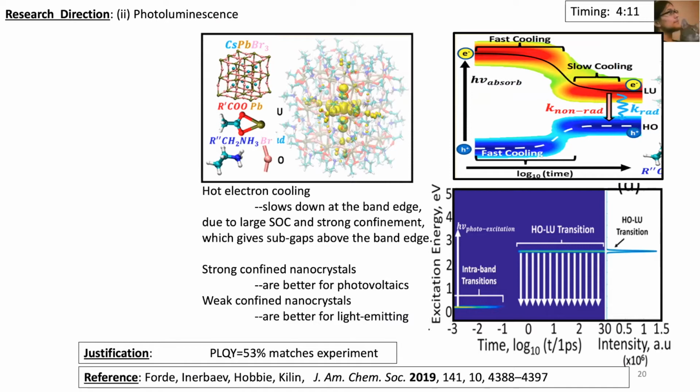And since it is an ionic crystal, one of the optimal strategies is use dual ligands. So one ligand coordinates with cation, another with anion. And here we modeled alkyl ammonium, and alkyl was very short, like just 2 carbons, and short carboxylic acid, and they were passivating surface in the alternating ways so that they do not let charge carriers away from this model, so they are truly confined.